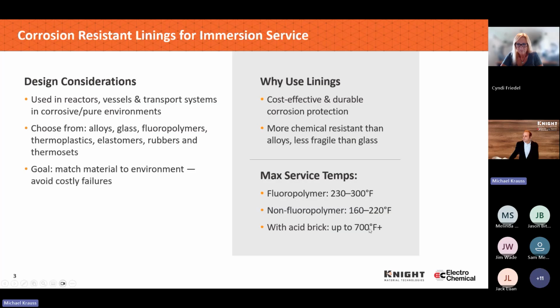And we'll look at service temperatures. And this is an area that is really tricky. We offer bonded sheet linings. So when we look at fluoropolymers, we typically rate them to about 300 degrees Fahrenheit. In some cases, the fluoropolymers might be able to hold up to a higher temperature, but the adhesive system and design can be the limiting factor. So it gives you a good idea around the fluoropolymer solutions, depending on specific chemical concentrations and service, in the 230 to 300 range Fahrenheit.